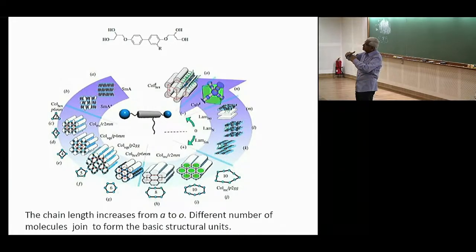Then you have the usual layer displacement U that costs energy. There is a coupling between these two that costs more energy. And then in a Smectic C, a twist or a bend within a layer can get coupled to a twist across the layers. In fact, this can give rise to some spontaneous breaking of chiral symmetry in some growth patterns, which we again found. We were the first to find it about 20 years ago, and we were the first to measure that relevant elasticity. So Smectic C is pretty complicated.